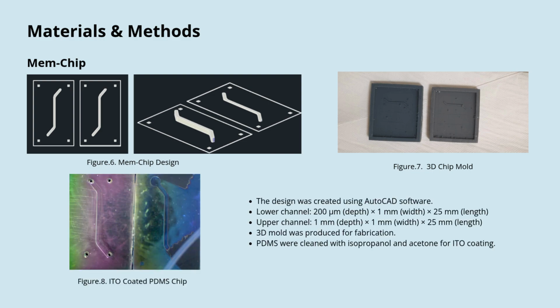It has two parallel PDMS channels. The lower channel has 200 micrometer depth, 1 mm width, and 25 mm length. The upper channel has 1 mm depth, 1 mm width, and 25 mm length. A pair has been sent for ITO coating with DC. PDMS were cleaned with isopropanol and acetone before the operation.